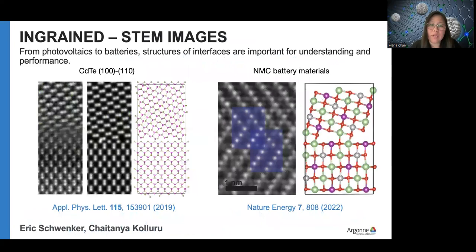Here are some examples for electron microscopy. On the left is the experimental image, on the right is a structural model, and in the middle you see the simulated image. You can see, if you're familiar with modeling, which you are, that there's something wrong with the interface, that the interface is not quite physical, and that's what's going to be solved in the next code. But Ingrained does a rough matching of the top and bottom part for interfaces, and tries to have a periodic structure, which is important for carrying out further simulations.